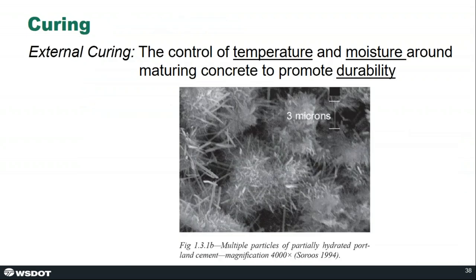So the next step comes the curing process. And just to clarify, when you say curing, we're talking about the controlling of the temperature and moisture around the maturing concrete as it hydrates to promote durability. So this is different from hydration itself. This is just to provide an environment where the concrete can achieve the properties as close to possible as what we can get in the lab.